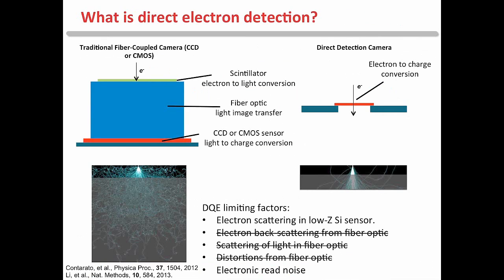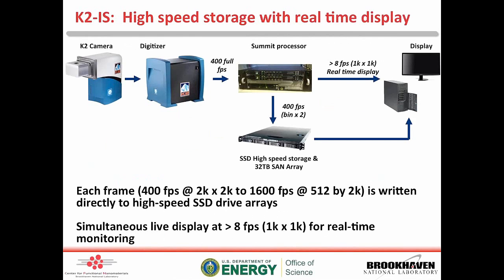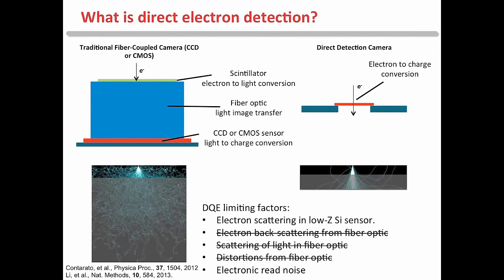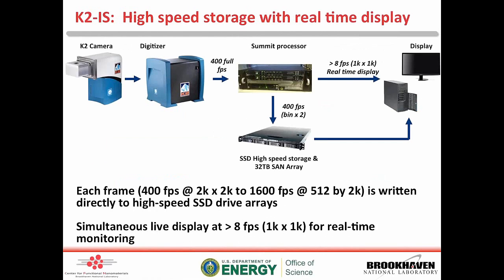So this has been predominantly used in the area of biological microscopy. Again, this AAAS meeting that this talk was first presented at had another beautiful talk from a biological microscopist showing all the ways that it's impacted that field. Really impressive stuff. But what we were interested in doing was trying to push this for high frame rate. If you have an improved detector, you can use it to do low dose imaging, or you can increase the dose and use this as a way to do high frame rate imaging. So we worked with Gatan, contracted them out to see how far they can push on this, and they created this K2 in situ or K2IS camera.